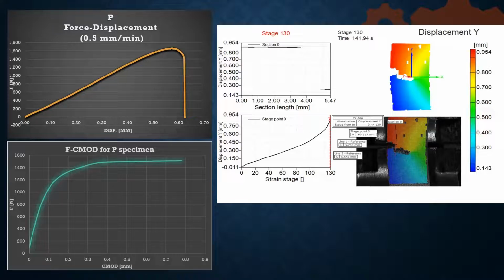In the diagram on the left side of the slide, we can see the dependence of force on displacement and force on the CMOD parameter. On the right side of the slide, we can see one report image from the Aramis software on which we can follow the displacement area on the recorded specimen. It is important to note that no stable ductile crack growth is observed. Therefore, for this material, the focus was on determining the value of the stress intensity factor.